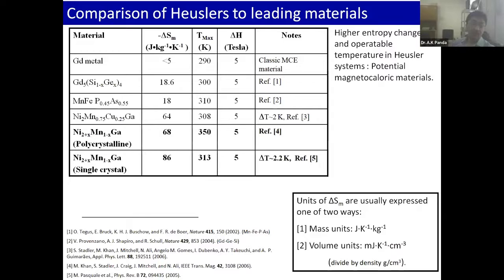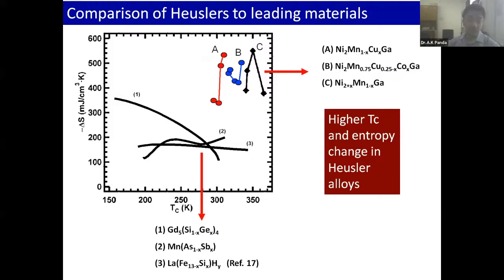But nevertheless, we have a proper incorporation. We can reduce the transformation temperature. So basically, the idea is we try to do away with some conventional materials and jump into making some nickel-based materials of different compositions, right? And this is how the entropy plots would look when we compare them. So when you have nickel, manganese, copper, gallium, or nickel, manganese, gallium, they are far above in TC and entropy change in Heusler alloys. So you can bring about high temperature transformations here, and that is desirable because you can tailor it to bring it to a near room temperature transformation.